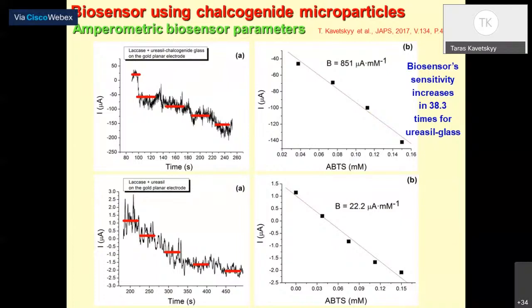When we compare the biosensor's parameters with the pure ureasil matrix and with matrices with chalcogenide phase clusters, we found that the sensitivity of biosensors increases 40 times. Next slide.